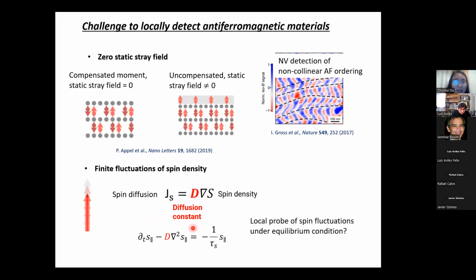And also, if we look at the time-dependent spin density, we can see that it is also correlated with the spin diffusion constant. So if we use NV center to measure the time-dependent spin fluctuation of the spin density, we can directly reveal the spin diffusion constant by solving the spin diffusion equation. So this is our mechanism. Next I will show you that indeed we can use NV center to measure the spin diffusion constant. And because we measure the fluctuation of the spin density in thermal equilibrium condition, this means that we can measure the spin transport properties non-invasively without making electrical contact to the material.